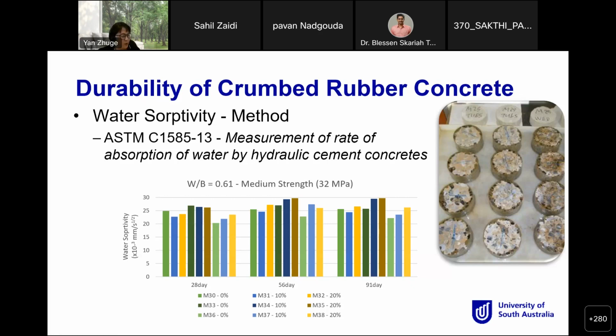Both M34 and M35, that is 10 and 20% with fly ash mix, you can see for M34 and M35 the trend is very similar to mix M32, so the fly ash effect is not that significant. And mixes M37 and M38 both show a higher water sorptivity than the control mix at all the ages tested. So this trend appears to be an approximately linear increase in water sorptivity with the rubber content at 28 and 91 days tests.